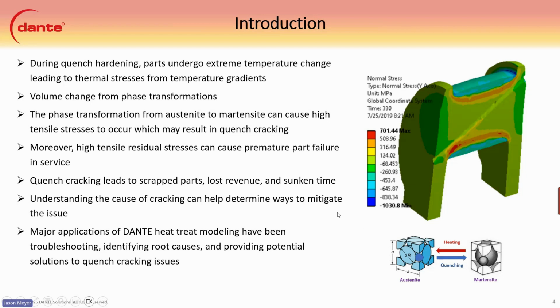These high tensile stresses can cause premature part failure in service. And then quench cracking leads to scrap parts, loss of revenue, and sunk time. So it's a big concern. Understanding the cause of quench cracking can help determine ways to mitigate it. And the major applications of DANTE over the years have been troubleshooting and identifying root causes and providing potential solutions to quench cracking issues.